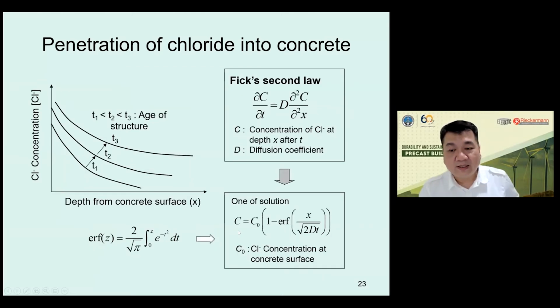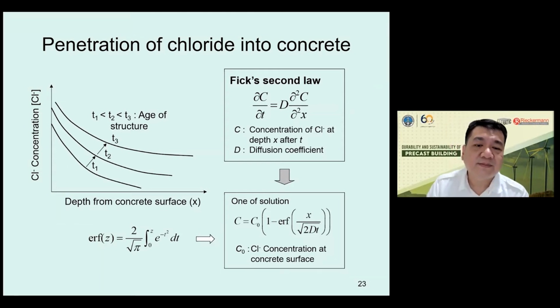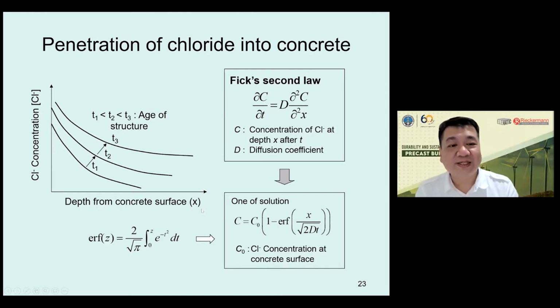So differing from the carbonation, the chloride penetrates faster, but we can find chloride in the marine environment only, and maybe in some countries using the de-icing agent. The penetration rate of chloride follows Fick's second law. This is some theoretical background, but just for information.